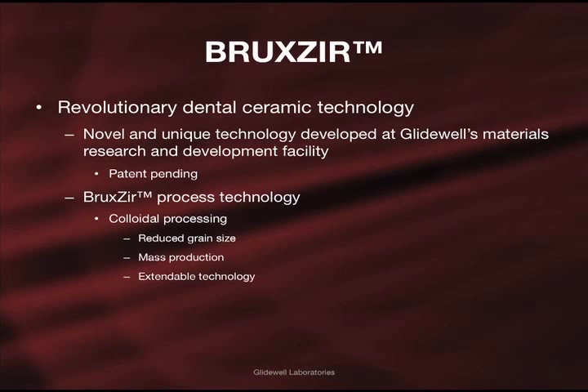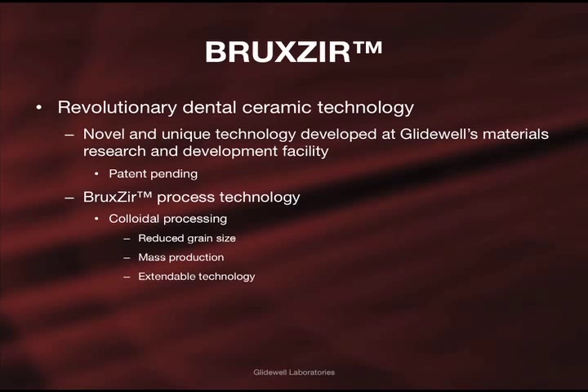BruxZir is an exceptionally unique zirconia material. The material process starts with the very best zirconia powder material available today, produced by Tosoh in Japan. Then through our proprietary, patent-pending process, the zirconia nanocrystals are further reduced by colloidal processing. This uniquely engineered ceramic process results in a further reduction of the starting zirconia grain size, resulting in a substantially smaller sintered grain size compared to more conventional zirconia processing, such as cold isostatic processing or uniaxial pressing.